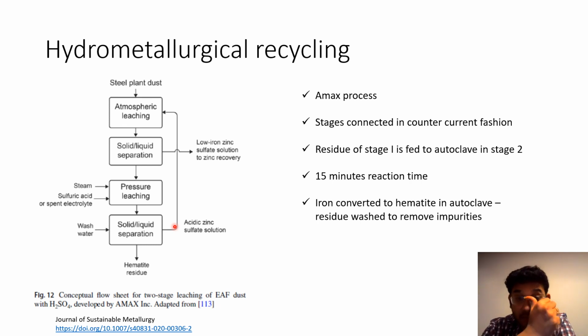What happens is that iron gets converted into hematite inside an autoclave, not a goethite, not a lepidocrocite. Those are hydroxides. You can deal with them, but hematite is much better. It can be used straight away in other processes, and it's very easy to filter out. So they managed to wash away the impurities. It's a hydrometallurgical step, and of course you have a generic solid-liquid separation step here. You could use solvent extraction, or other types of processes, and then probably electrowinning, and then get the acid zinc sulfate back. Okay, and that's it. It's quite a simple leaching process.